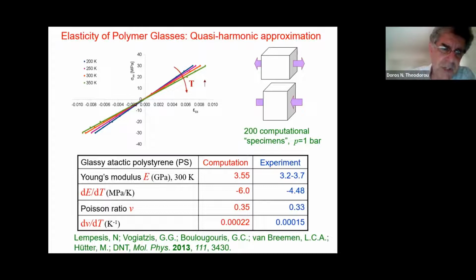You can also change the temperature and probe how these properties change with temperature. Of course, the higher the temperature, the softer the material will become. And here are shown the temperature derivatives of the Young's modulus and the Poisson ratio, which are certainly not in perfect agreement, but they are quite close to what one sees experimentally. So this idea of using the quasi-harmonic approximation within the basins where the system is trapped gives us a good handle on the elastic properties of a glassy polymer.